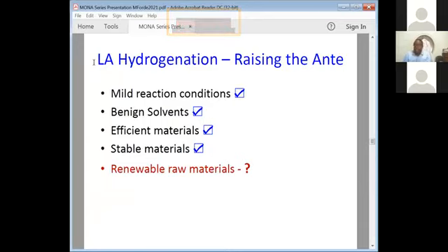So I have mild reaction conditions, the solvent is okay, the materials seem to be quite efficient, they're stable, but there's a problem. The problem is that I'm not necessarily using renewable materials all the way. So we went back to the ideation board: hydrogen with any substrate, levulinic acid, furfural, whatever, in water, and we can actually get good selectivity to products, and we're using furfural because we're going to switch to that now. The hydrogen is coming from natural gas primarily, and we don't want that, of course, because the co-product is CO or CO2, depending on how they get the hydrogen out. And of course, natural gas means that we have to have the resource in order to do the reaction.